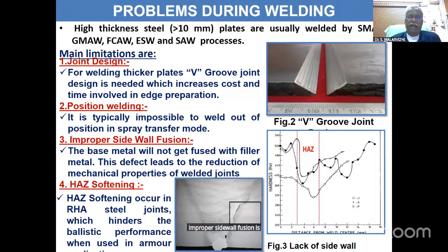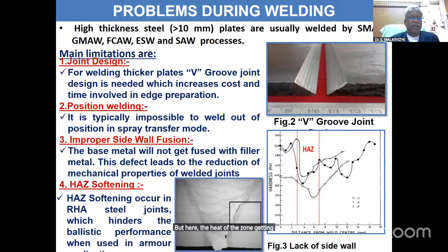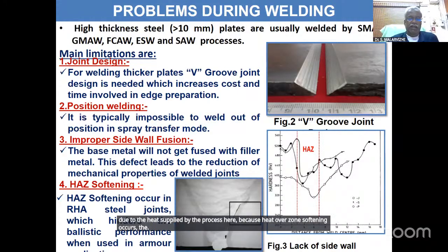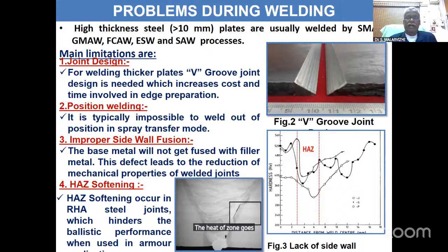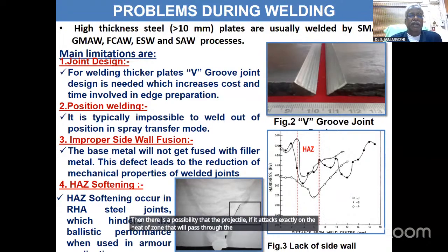Especially in rolled homogeneous armor steel, RHA steel, heat affected zone softening is another problem here. Normally, the heat affected zone will have higher hardness, but here the heat affected zone gets softened due to the heat supplied by the process. Because HAZ softening occurs, the HAZ goes below the hardness level of the base metal. Then there is a possibility that if the projectile attacks exactly on the heat affected zone, it will pass through the base metal. So these are the problems.